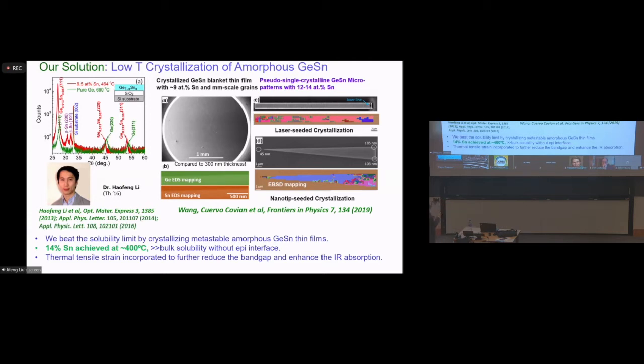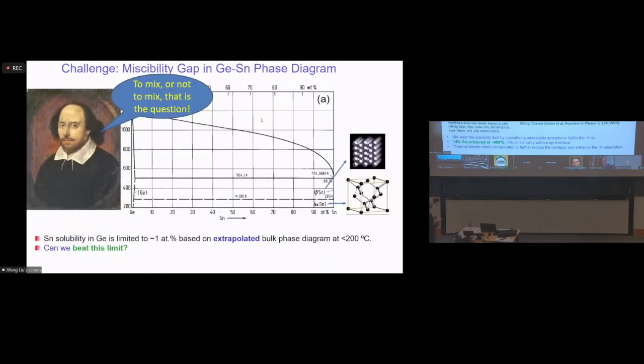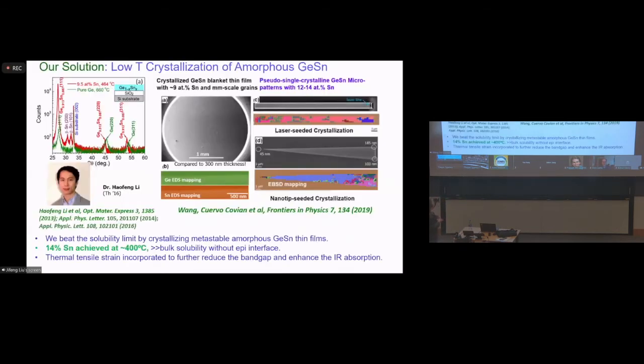So that means the nucleation is relatively slow and lateral growth is really fast. That fast lateral growth is enabled by this eutectic phase diagram, where once you are above the eutectic temperature, you introduce a tiny amount of tin droplets, a liquid phase, that enhances the atomic diffusion at relatively low temperatures. And once the tin segregates to the surface, you can etch it off with hydrochloric acid. Using this approach, we can also grow on a smaller area where the crystallinity is much better. You don't have the large angle grain boundaries anymore. All you have are coherent twin boundaries.